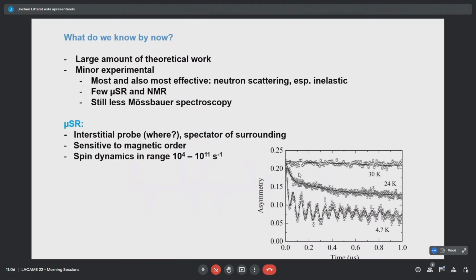Now, let's turn to the muon spin rotation. As you know, that's the interstitial probe. The muon is implanted in between the atoms, so it will be a spectator of its surrounding. It will be sensitive whether the surrounding is ordered or whether it's fluctuating, and then it will reflect at which frequencies these fluctuations take place. That's typically between 10 to the 4 and 10 to the 11 per second. So relatively slow in comparison to the neutrons.